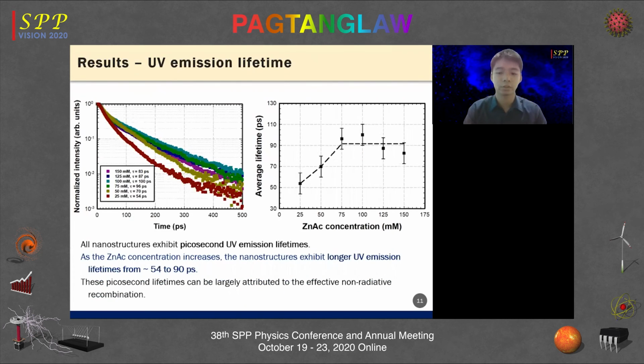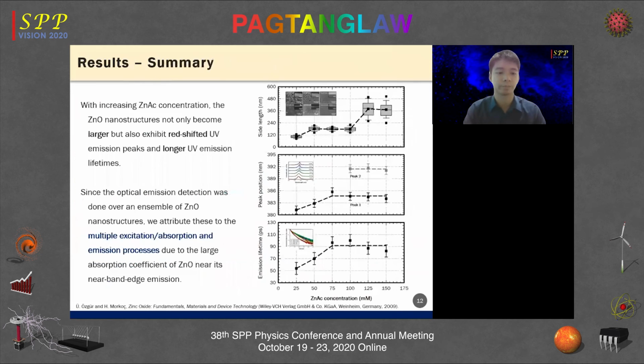Moreover, this slide shows the UV emission lifetime of the hydrothermal grown zinc oxide nanostructures. All the nanostructures exhibit picosecond UV emission lifetimes, and as the zinc acetate concentration increases, the average emission lifetime increases from 54 to 90 picoseconds. These picosecond lifetimes can be largely attributed to the effective non-radiative recombination with the activation of non-radiative centers at room temperature. With increasing zinc acetate concentration, the zinc oxide nanostructures not only become larger, but also exhibit redshifted UV emission peaks and longer UV emission lifetimes.